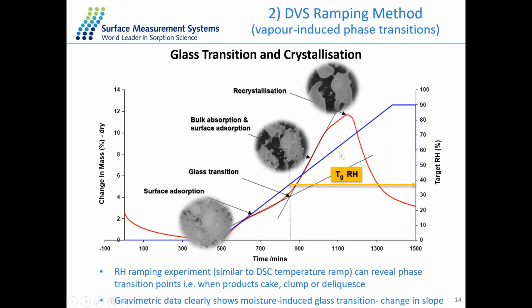And as the humidity keeps increasing, we can also notice there is a point where the sample will decrease in mass dramatically. And this is due to the recrystallization of the sample, as the crystalline state has smaller surface area as well as less sorption capacity. So with this single plot, we can get one point for the glass transition and another point for the crystallization for the material at certain temperature, and here it is 25 degrees.